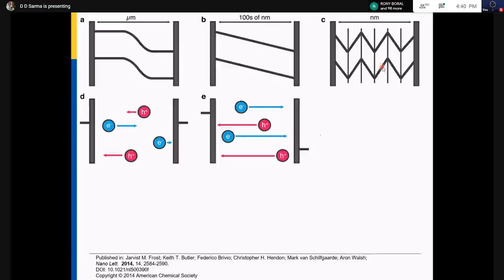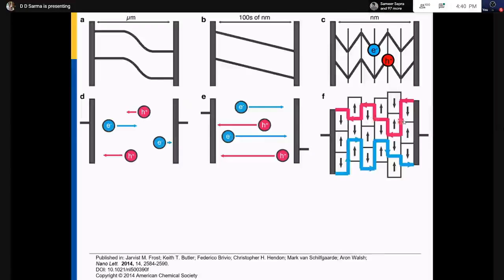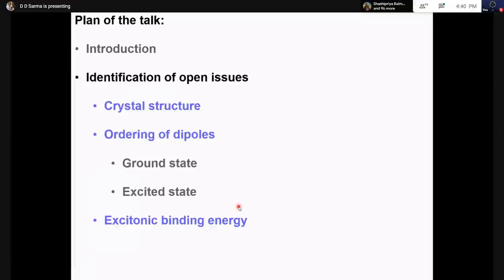What would happen? Imagine that you create the electron and hole here. The electron goes there, the hole comes here. The hole will climb up there, the electron will climb down there, so that it doesn't matter where you create the electron and hole, the hole will go and sit at these top positions and the electrons here, so that they are physically separated across this domain very quickly. And then they'll find the path along the domain boundary which minimizes the energy for the hole and which minimizes the energy for the electron, and then they'll follow different paths avoiding each other, and therefore the efficiency will go up in a ferroelectric material.